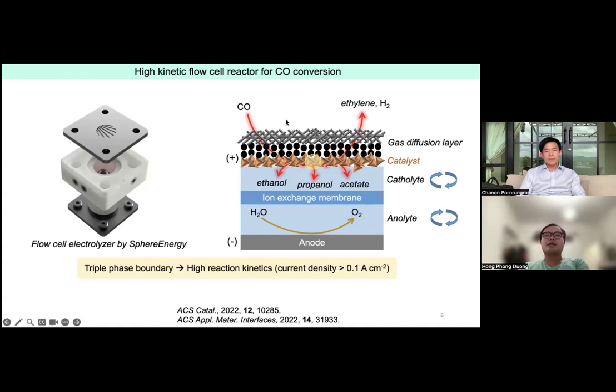On the other side we can flow CO or CO2, but in this case I work with CO. In the gas phase, we usually get ethylene as the main product, and hydrogen. Of course, we always get hydrogen, but it's just a question of how much. Then in the liquid phase, we have ethanol, propanol, and acetic acid, and those are usually the main products from CO reduction. In between the cells, we also have an ion exchange membrane. It can be either an anion exchange membrane or a cation exchange membrane like Nafion.